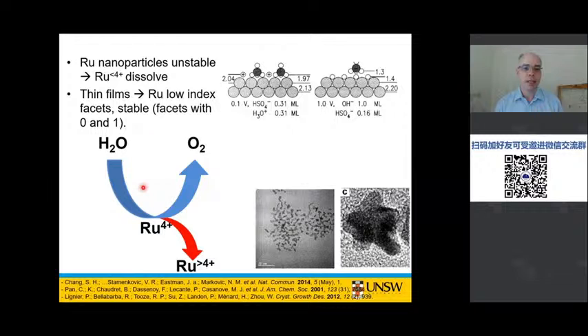And as I say, the problem with ruthenium is it does tend to be unstable when it's oxidized and catalyzing for the oxygen evolution reaction. So we have to oxidize ruthenium up. And when it gets to these high oxidation states, it's very, very easy for it just to dissolve up, as I said, and go into the acid electrolyte.